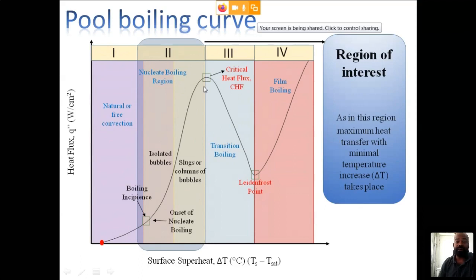This is the critical point above which any system should not be operated or cannot be operated, because above this, burning or system failure will take place. That's why the whole research is lying on increasing this point. For example, if the corresponding heat flux is this one, then you have to take measures or efforts to increase this critical heat flux by doing some modification. Also, if you can increase the slope of this curve, then it is advantageous.